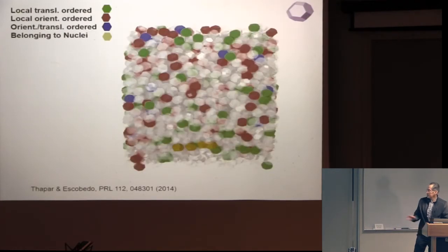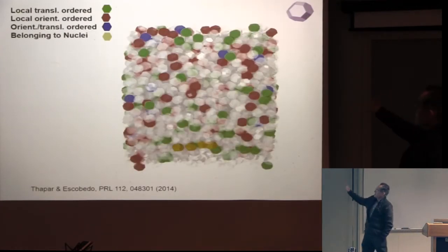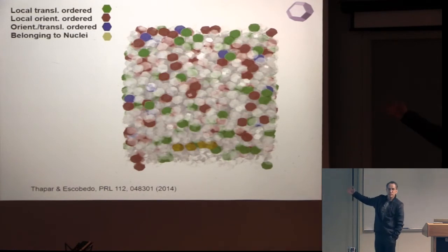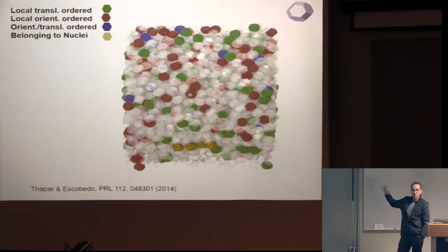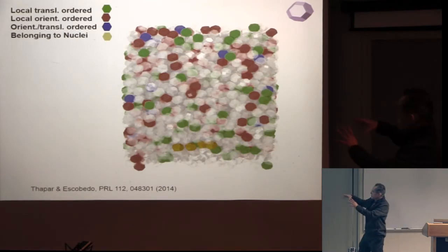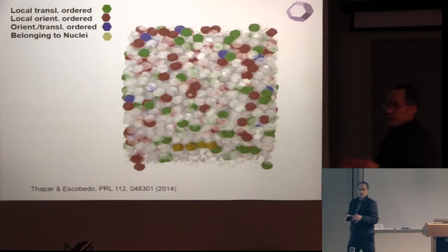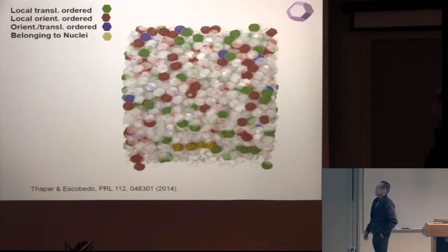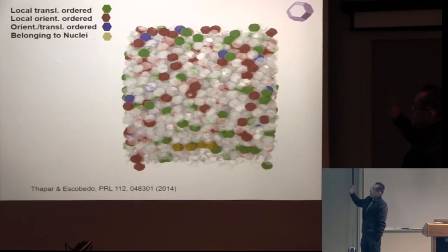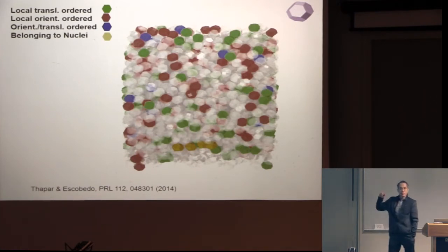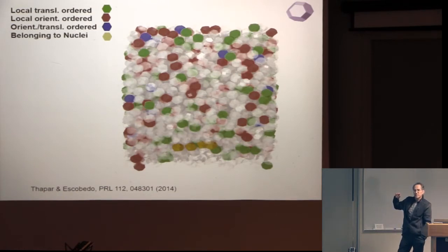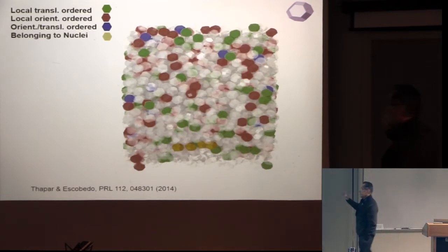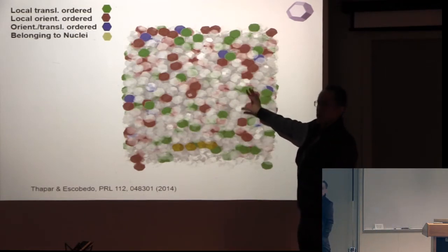Now, I mentioned in this example that we initially expected the rates of this process would be similar to hard spheres for the same degree of supersaturation, right? Because in both cases, you have these rounded objects forming a phase that has translational order. In one case, FCC, in this case, something a little different. And yet we find that in this case, it's much faster. Now, there are other shapes where it's much slower. You can measure it, but making sense of that has to do with really making sense of what happens in the isotropic phase.